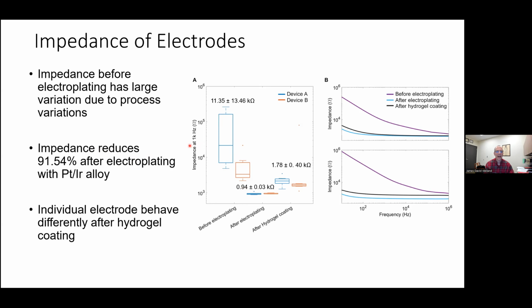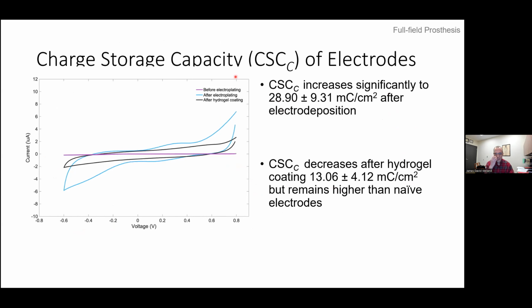What we see after electroplating, which is this data here, is that we've reduced not only the impedance overall, but also the variability. So electroplating had a cleaning effect. Adding a hydrogel layer on top of the electrodes, we were worried that would effectively insulate the electrodes, but hydrogel actually has a reasonable conductivity, so that only increased the impedance of the electrodes a small bit. And this shows some impedance spectra in two individual cases. Charge storage capacity is an important factor for stimulating electrodes, and we've shown, without going into too much detail, that the purple line is before electroplating.